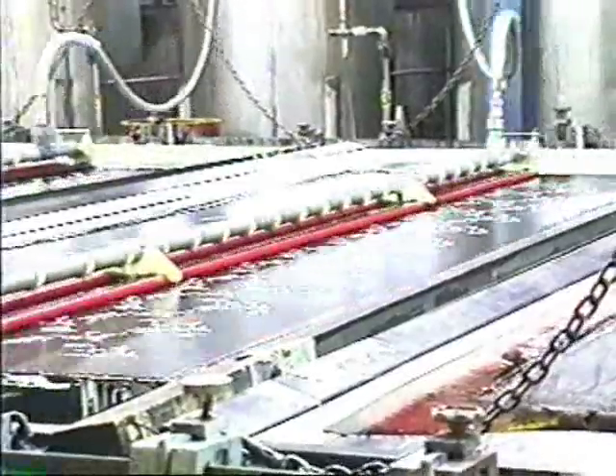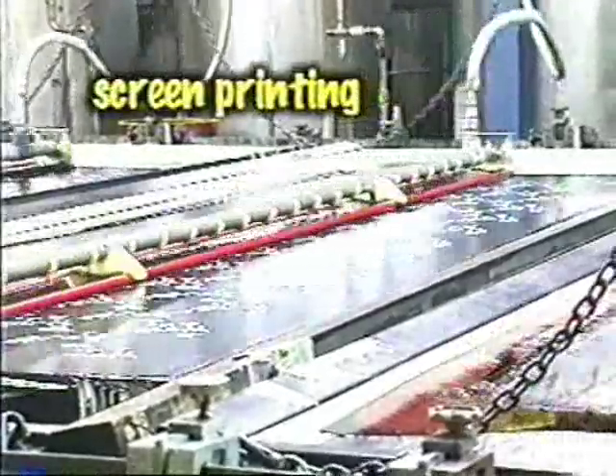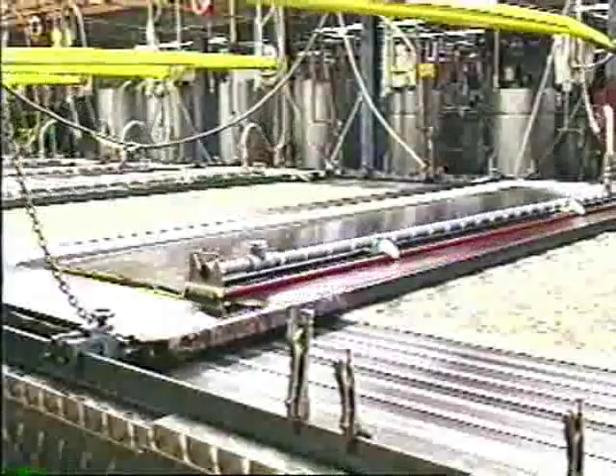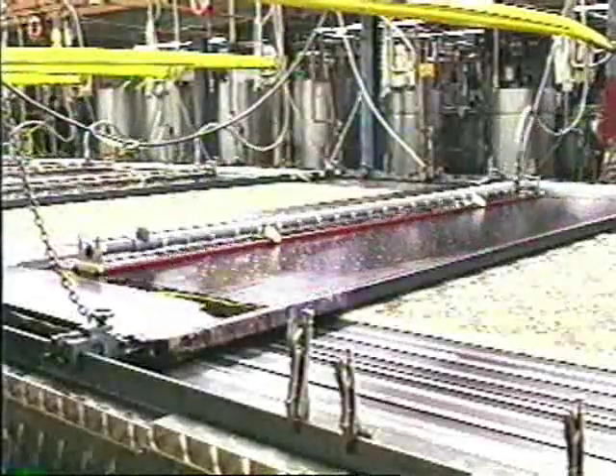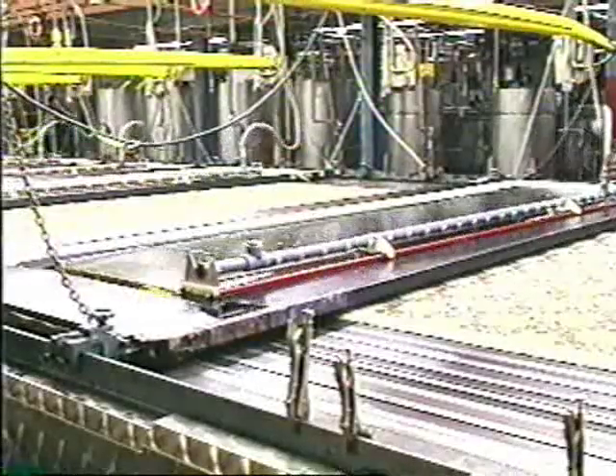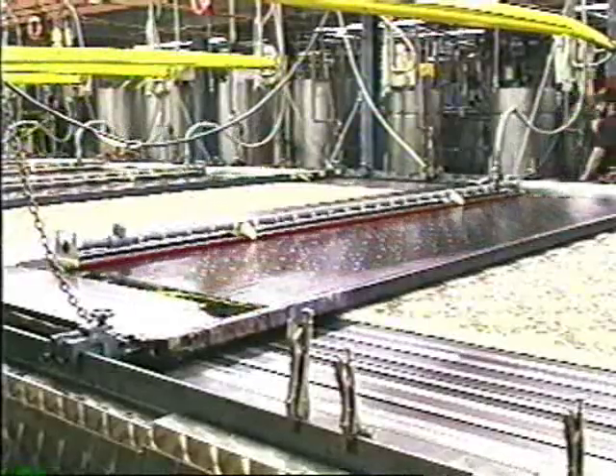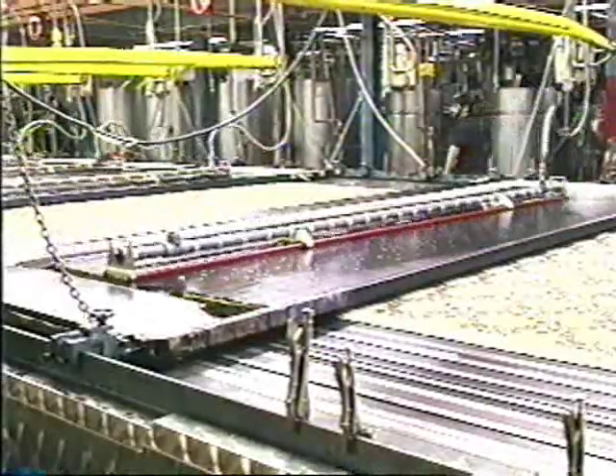Color and patterns may be added to carpets by a screen printing process after the carpet is tufted and backed. Coating or backing these products before dyeing provides more stability during printing. Using multiple screens, the colors are printed from lightest to darkest in order to avoid layering of colors that may produce undesired effects in the carpet. During the finishing process, shearing removes loose or projecting fibers and surface lint from the face of the carpet fabric to achieve the desired tip definition of the yarn.